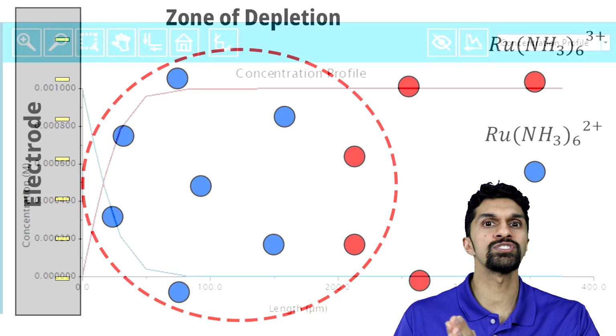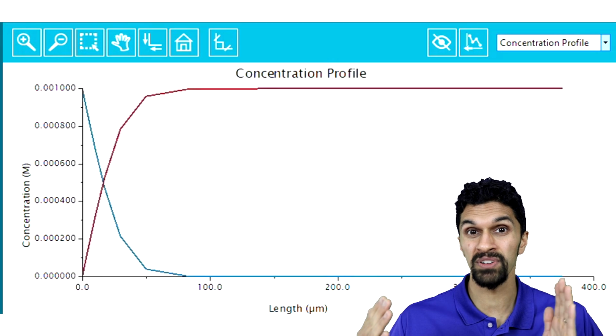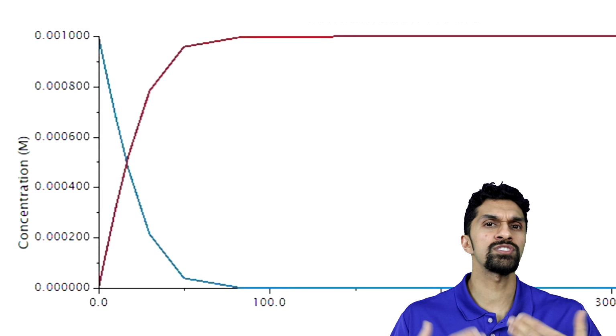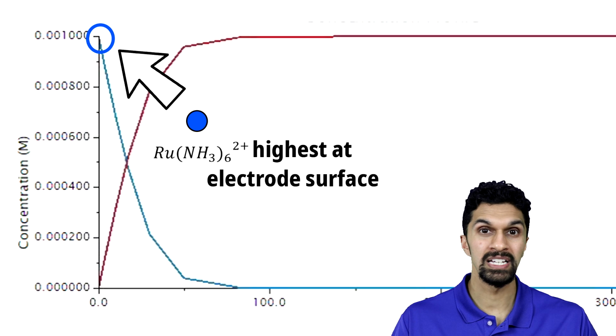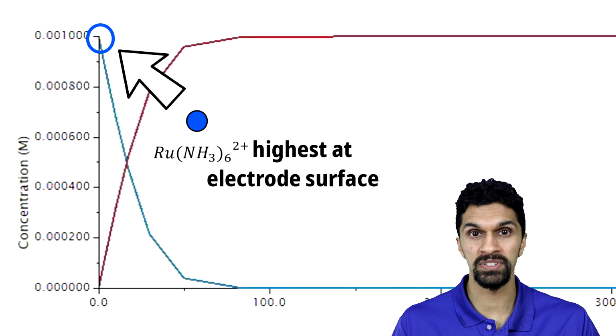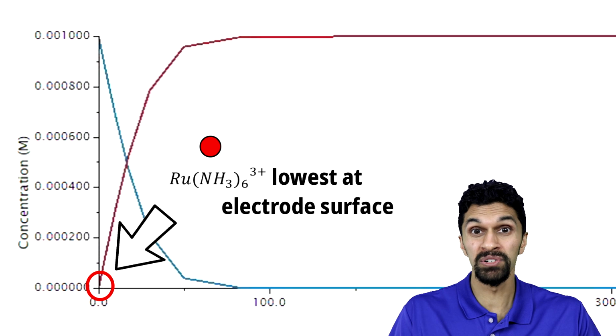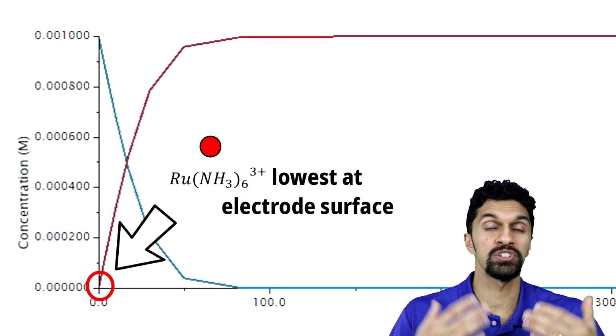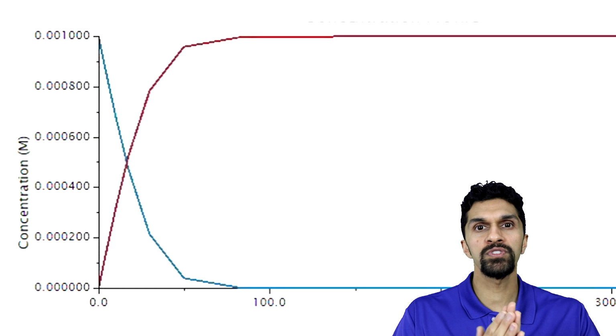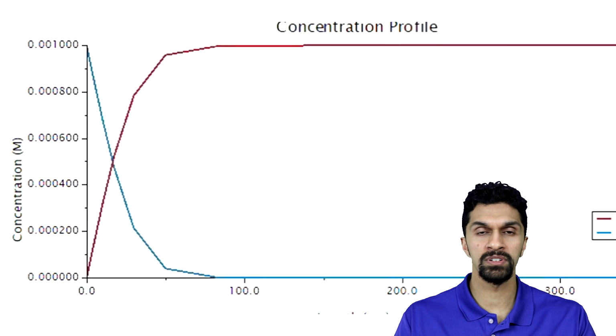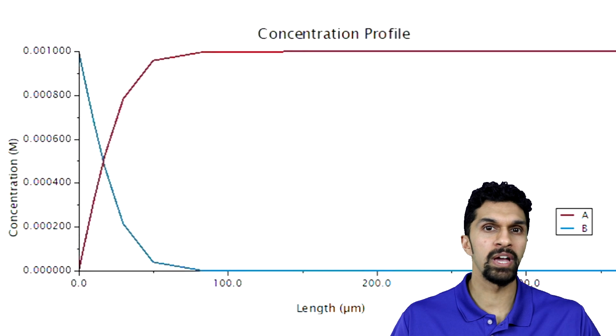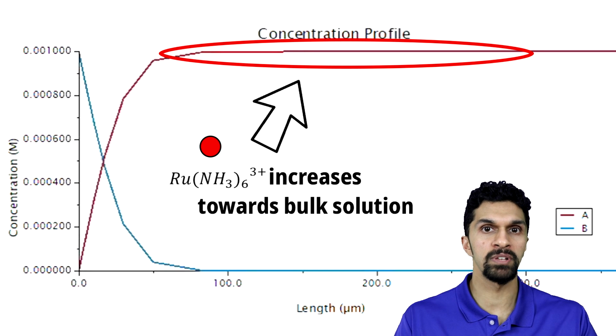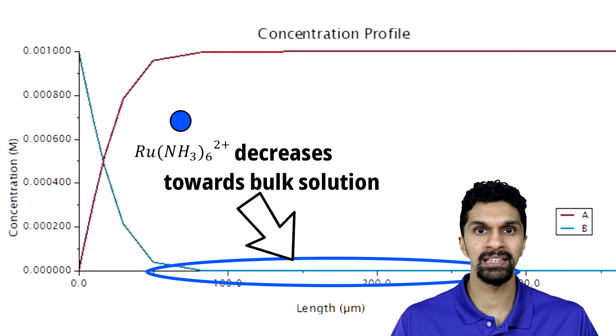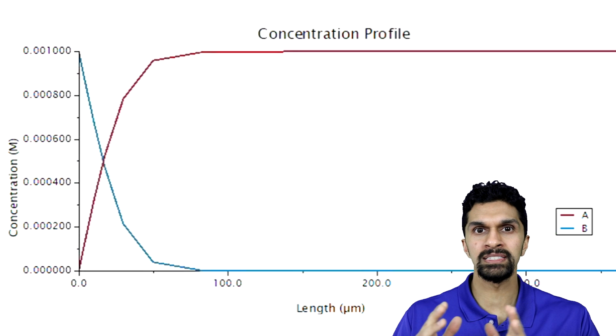If we look at the concentration profile as a function of the distance from the electrode, you'll see that the concentration of ruthenium hexamine 2+ is highest at the electrode surface, and the concentration of ruthenium hexamine 3+ is practically zero at the electrode surface, or at least close to zero. As we move further away from the electrode surface into the bulk, the concentration profile starts to change. We have more and more ruthenium hexamine 3+ as we go into the bulk, and less ruthenium hexamine 2+. However, this is just a snapshot in time.